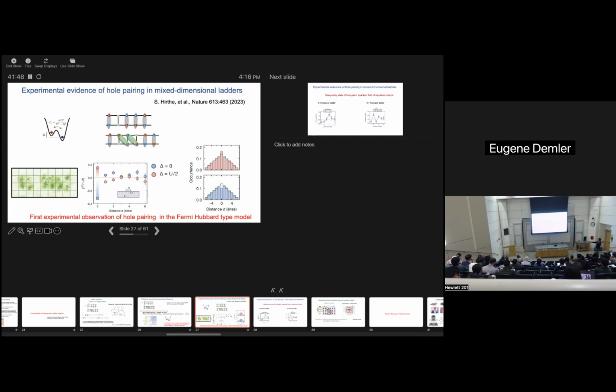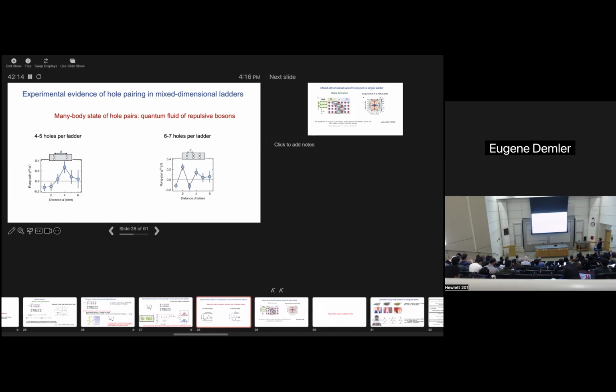And it's entirely driven in this case by magnetic energy, because we're dealing with a regime of strong J-probe. And so if we start with a configuration of strong singlets, but now the holes separate, then clearly our singlets are no longer benefiting from the exchange energy. So that's kind of a direct example of binding driven by magnetic interaction. Well, okay, and then if they add more holes, they can see that these pairs can start behaving as bosons with repulsive interaction on the ladder. They try to stay away from each other.